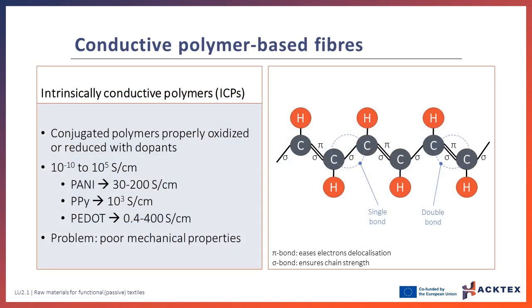Conductive polymers can conduct electrical charges due to a combination of favorable bond configuration and dopant agents. Among all intrinsically conductive polymers, the best candidates for polymer-based conductive fibers are polyaniline, polypyrrole, and PEDOT. As shown, they can reach a broad range of conductivities, but their conductivity is lower than that provided by metals and carbon materials. Conductive polymers are lighter and more flexible, making them more suitable for textile applications, but their transformation into fibers is still a challenge, as the fibers obtained present poor mechanical properties. In commercial solutions, conductive polymers are used as coatings rather than as fibers.